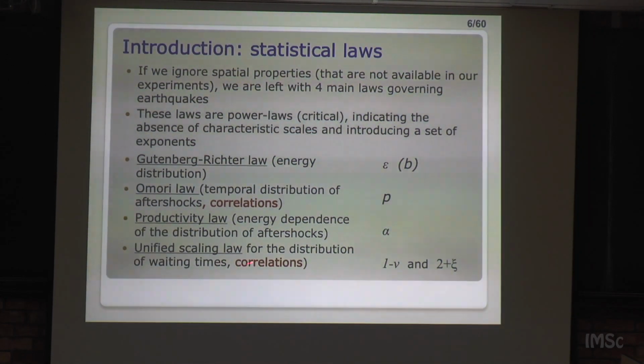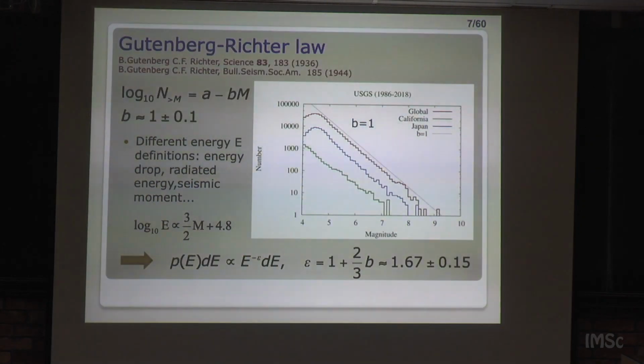And then there is a fourth law which is more modern. This was proposed only less than 10 years ago. That is called the unified scaling law, that has to do with the distribution of waiting times, so times between earthquakes. Okay? And this law is special because it's a double power law. It introduces two exponents, 1 minus nu and 2 plus xi. So we think that this set of exponents characterizes the criticality in this problem, and I will now revise them so we can see exactly what they mean, okay? So the Gutenberg-Richter law, you probably everybody knows. This was proposed by Gutenberg and Richter in the early 20th century.